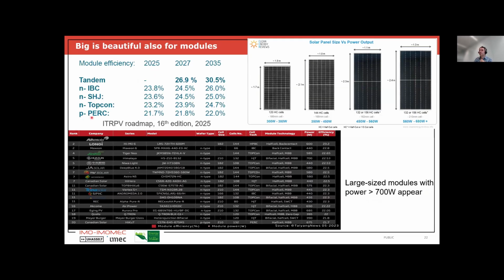So you see for the PERC, which we produced in the past, it is around 22%. But for TOPCon and silicon heterojunction, we are way above that with more than 23%. And we're getting close with the back contacts to 24%. And that's why PERC is being produced less and less, because the efficiency is much smaller.